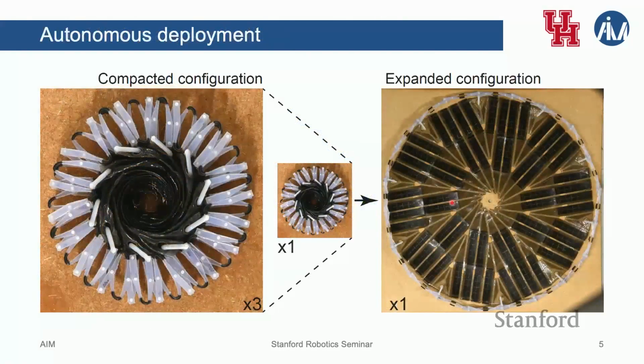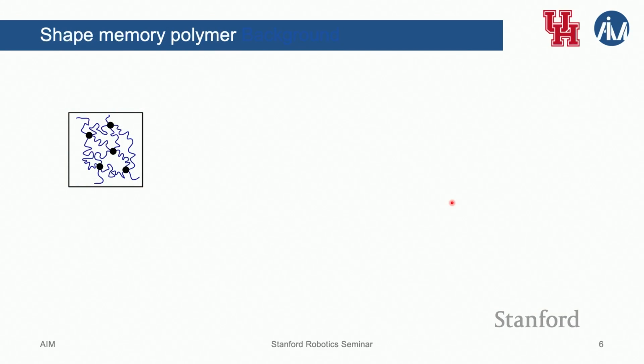The first one, this is the result. It's entirely 3D printed, and you can see the middle and to the right are both 1-to-1 scale. So this is the amount of expansion we get. We were targeting exactly a 10-fold areal expansion, and that's what we got. And the notion is we can go from the center to the right without any human interaction. It would just autonomously expand. And we achieved this through the 3D printing of shape memory polymers. So shape memory polymers is a fancy word for many, many thermoset resins, which all exhibit this phenomenon at different temperatures. The idea is we're going to 3D print something like this.